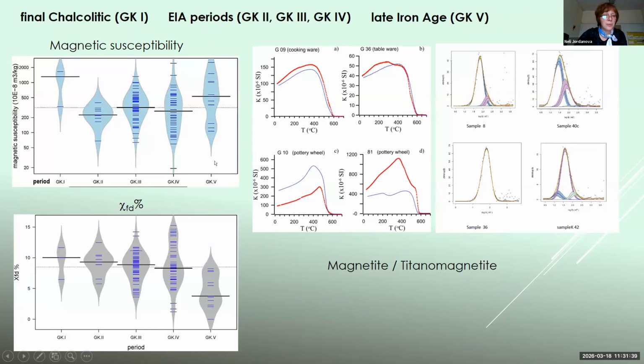So here I plot magnetic susceptibility and frequency-dependent susceptibility according to the periods of the culture when the ceramic was found. So the final Chalcolithic is characterized by higher susceptibilities, very varying values were obtained for the early Iron Age periods, and relatively higher values were obtained for the late Iron Age ceramics. In contrast, frequency-dependent susceptibility showed lower values for the wheel-made ceramics, while for the others we obtained bigger scatter in the data. Again, magnetite was identified as the main magnetic carrier, or titanomagnetite.